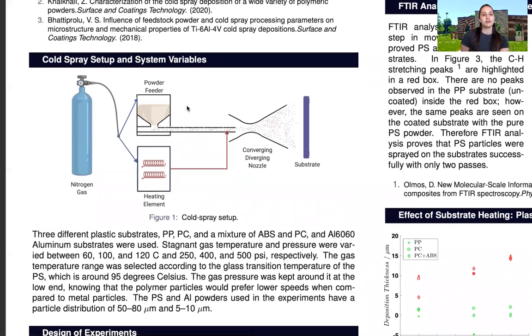Figure 1 shows a basic schematic of the cold spray setup with the nitrogen gas, powder feeder, heating element, nozzle, and the substrate. Although this figure shows the substrate vertically, our substrate was oriented horizontally and the nozzle perpendicular to the substrate. We changed the gas temperature between 60 to 120 C to stick around the glass transition temperature of polystyrene, which is around 95 degrees Celsius.